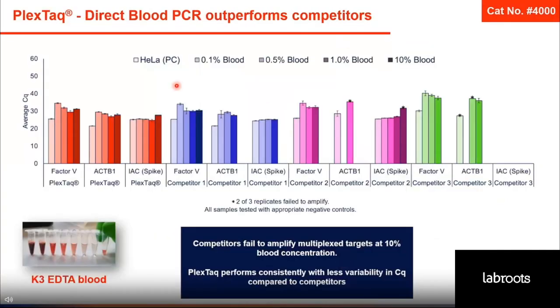Just to show you how well PlexTaq performs with blood, this is an example of an experiment where we compare performance of PlexTaq with 3 other competitors using 4 different concentrations of blood. This is starting with 0.1% of blood up to 10% of blood. And we were trying to detect 3 targets, 2 targets from blood. This is coagulation factor 5, actin B, which is a housekeeper, and we also additionally spiked the blood with internal control. So as you can see, PlexTaq was the only mix which performed consistently with less variability in Cq values with all blood samples. It was the only one which was able to amplify all of these targets in 10% of blood, whereas competitors either fail completely to amplify in this high concentration of blood, or they failed to amplify all of the targets.